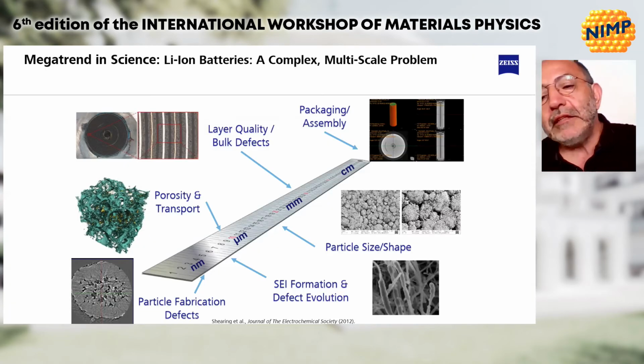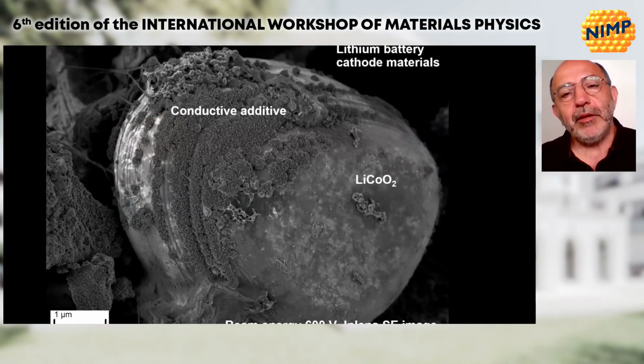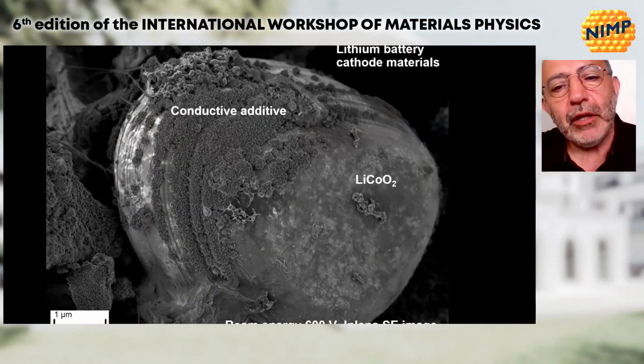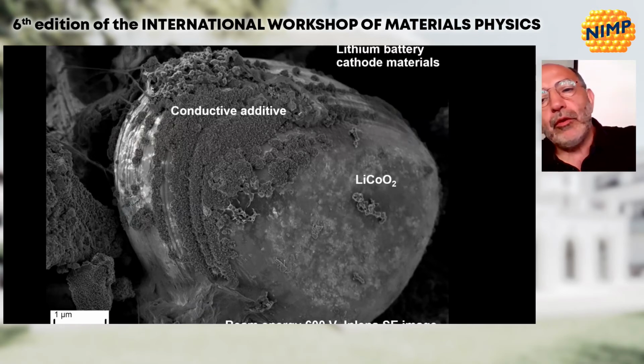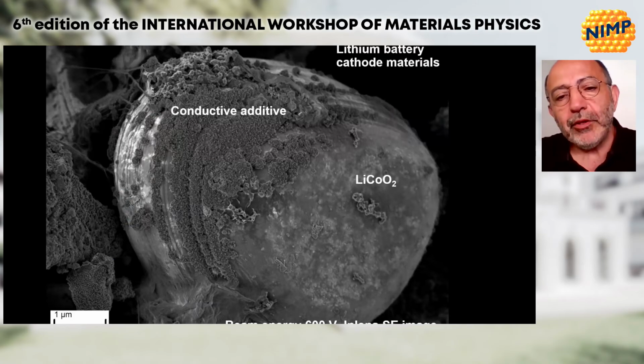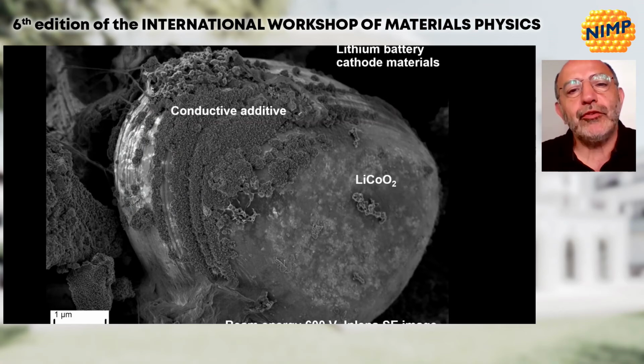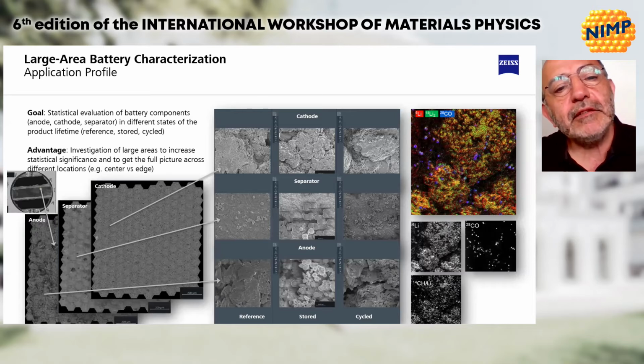We have details, for instance, in this particle, but we are missing the context, because we identify a particle, but we have no idea what the neighbor particles look like at 100, 200, or 1 millimeter distance. Why is this so important? Because we need to analyze all those particles in a huge context to classify the distribution, the shape, the change of the chemical composition by cycling of the batteries. And therefore, we will need, in this case, an image of a huge area.